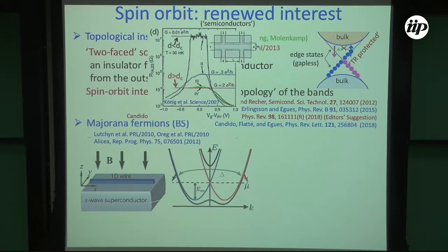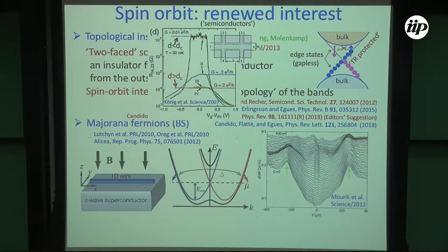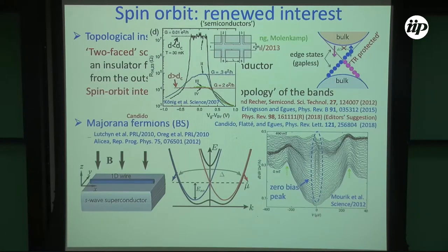The standard system looks something like a wire on top of a superconductor. Around 2012, there was a very classic paper. This is essentially measuring the conductance of the system — the density of states, which is essentially the conductance. What you see is the density of states of a superconductor, with the rise here, going down and back up — it's what they call a soft gap. What's new here is that the prediction from theory is that you would have a Majorana end mode localized right in the gap of the material, giving rise to a zero-bias conductance peak right in the middle of the superconducting gap.